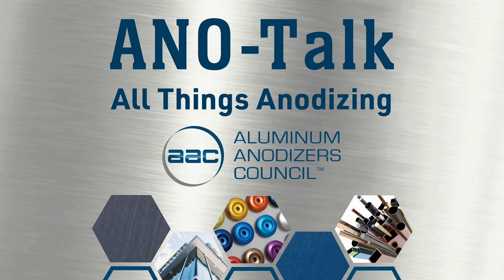Now, the thing that you mentioned earlier, we should go back to, so our viewers and listeners understand this. If you don't have the right surface area of contact between the rack and the part, you can get burning. And that has nothing to do with pulse anodizing. Yeah, you can make the argument that's anodizing. Well, I understand, but if you just put that rack in there and give it a lot of current density and you haven't considered racking, guess what? Right. For someone to go out there and say, I'm going to do 30 seconds this, 30 seconds that, you make sure your rack is properly set up. And in my experience, it's no problem, because most of the time the racks can handle higher current density. Maybe not if you go extremely high, but if you have a good racking procedure, so you have good contact points, you can do a higher current density than you think.